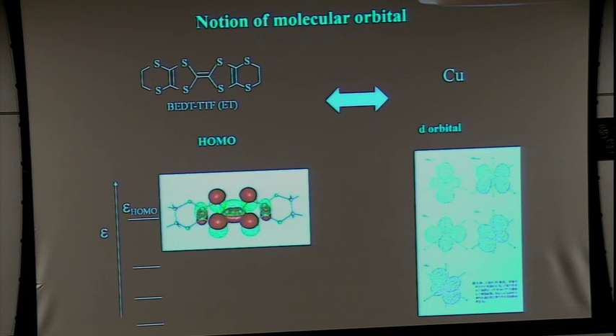For example, magnetic ordering in lanthanum copper oxide: the Mott insulating phase of the cuprates shows ordering at 200 or 300 Kelvin, but in organic materials it's 20 or 30 Kelvin. And Tc is 100 Kelvin in cuprates, but in our case 10 Kelvin. So all of the energy scales are one order of magnitude lower in organic materials.